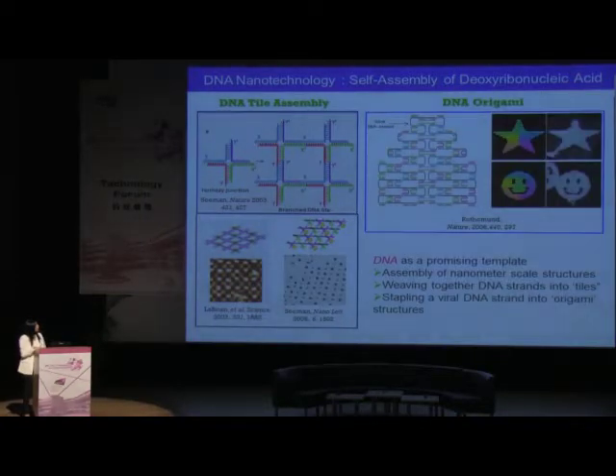And the second approach in this area we call the DNA origami approach. Basically, it's just taking a long, single viral DNA strand, and this strand itself folds into the desired pattern by adding different short staple DNA strands, shown here with the color. So once we have this kind of structure, basically you can see from these two approaches, DNA is the only molecule used for the assembly, and at the end gives you a very rigid and large DNA structure.